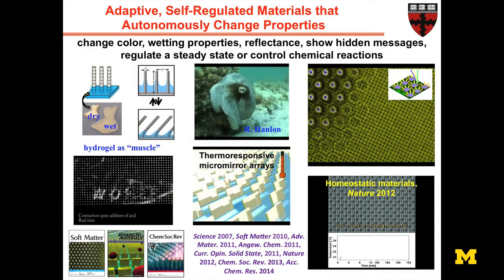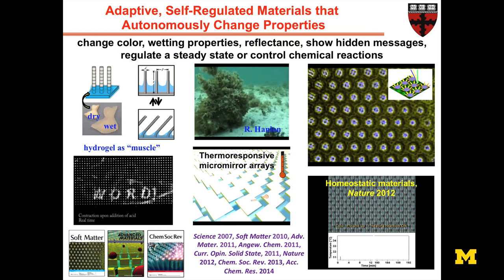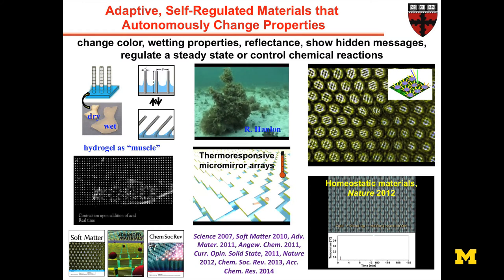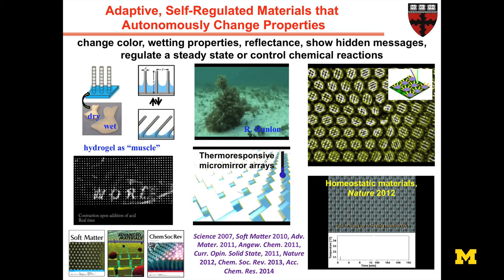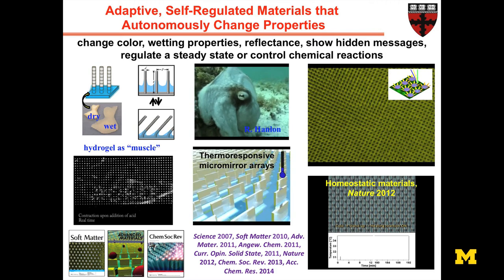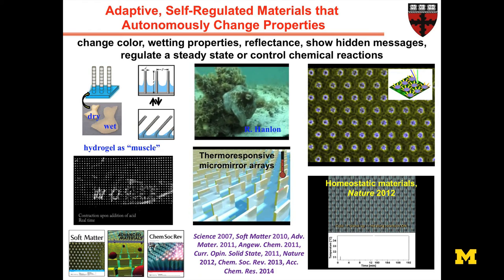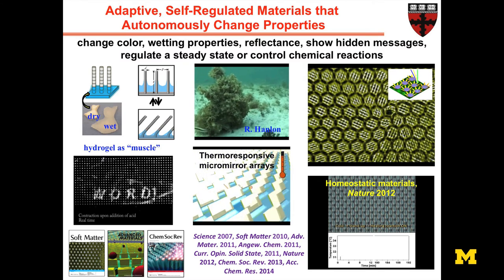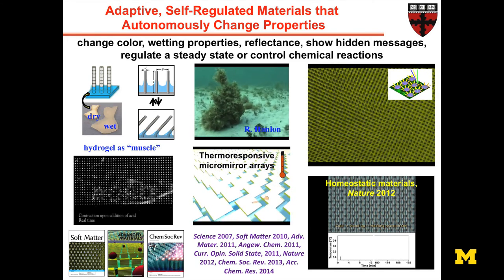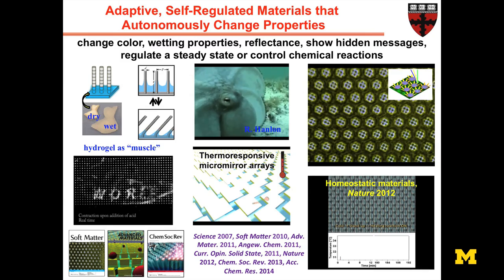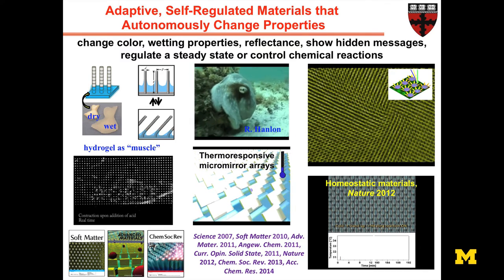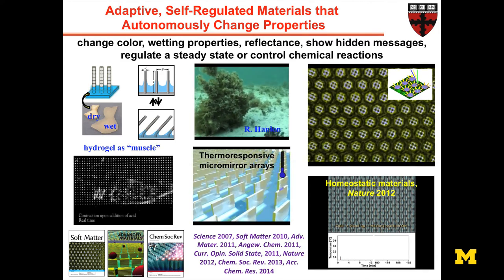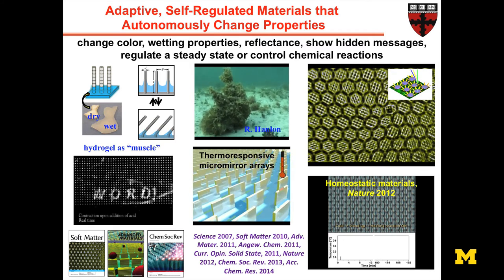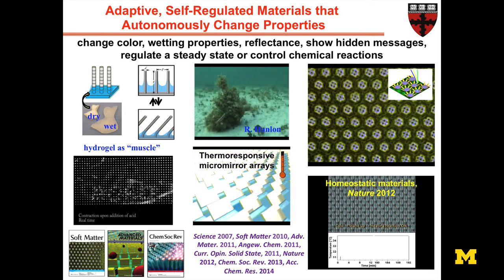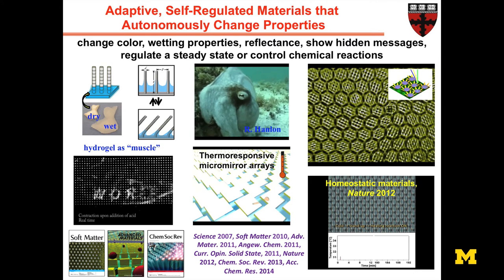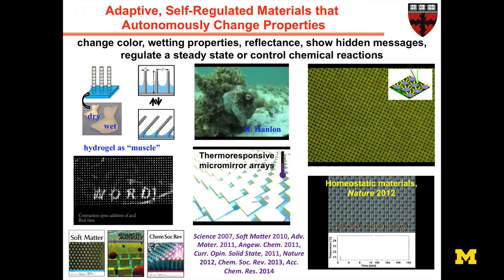And here's, again, just examples of the same surfaces where the gel is now holding a marker. And depending on the stretching of the marker, which in chemical words defines the concentration of your marker inside your gel, the words, or concentrated marker, will appear or disappear in response to, in this case, pH.